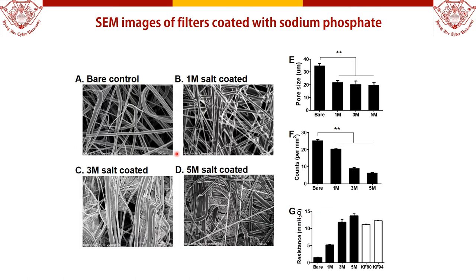Prior to the experiments using viruses, we looked at the characteristics of the coated filter. The coating of salt was observed between the fibers of the filter through scanning electron microscopy. The size and number of pores in the filter was reduced. To investigate the viability of filters, intake resistance was confirmed. The filter coated with the highest concentration salt showed similar intake resistance to the commercial mask KF94 in Korea.